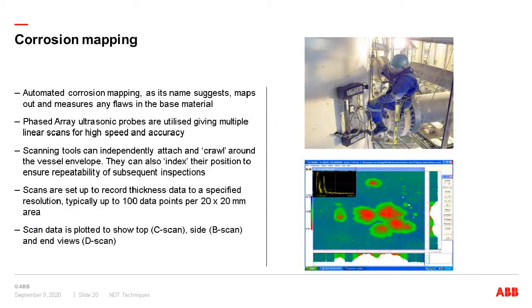Okay, so just a few examples of non-destructive testing. Corrosion mapping. This is an automated process. What we're looking for here is thinning of the vessel shell wall, and it maps out losses in material thickness. It uses phased array ultrasonic probes that give multiple scans at high speed and accuracy.